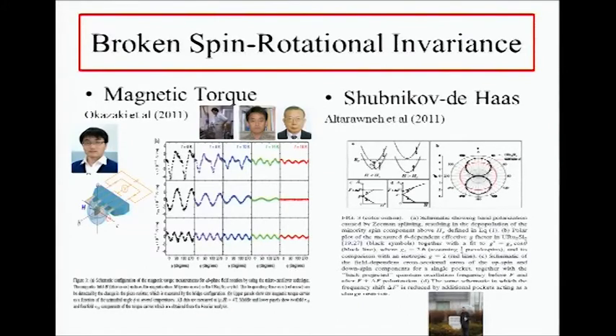Recently, some new clues have been thrown into this. Looking at magnetic torque experiments, you can see there's a clear change in the isotropy of the system. It's actually a tetragonal system, so there should be symmetry in the AB plane. However, at 17.5 Kelvin there's a change in the anisotropy. These are two experiments which show that at the low temperature phase, if you look in the plane, you see there's an Ising-like anisotropy in the G factor.